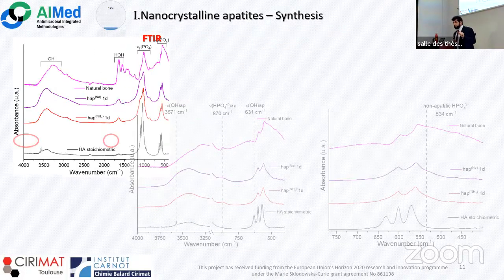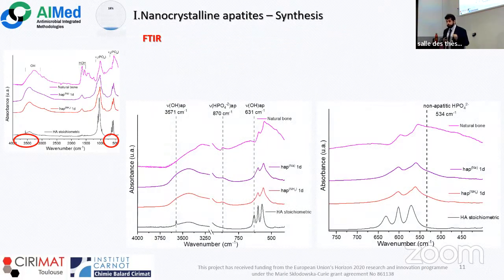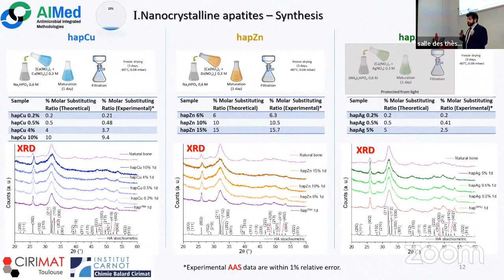We can make a small zoom on two zones to further demonstrate the non-stoichiometry of the crystals. And in fact, we can observe the decrease of the apatitic OH band and the appearance of the non-apatitic HPO4 bands. This synthesis is the basis of the synthesis of the three monosubstituted apatites that we show here.